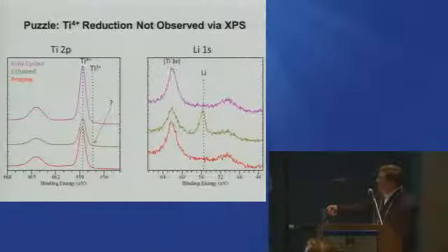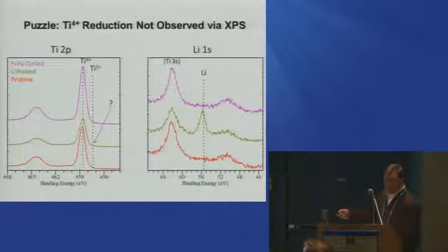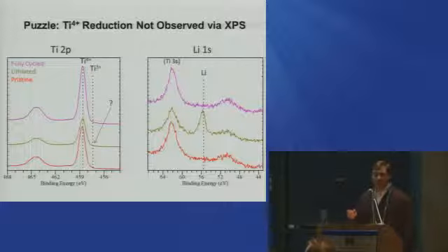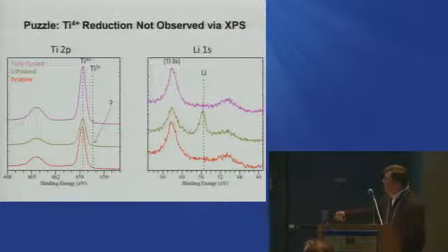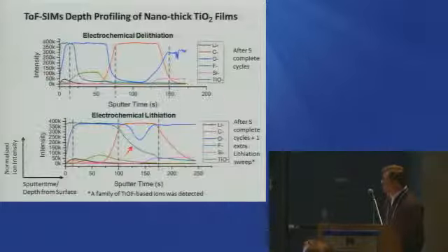But if you look at the actual XPS of lithiated anatase, these thin films, versus the delithiated ones, we actually see no change in the oxidation state of titanium. And so it's not just that we reduce titanium 4 to titanium 3 and it turns blue; there are other trapping mechanisms that don't report on the change in the oxidation state. And so in this particular case, XPS really isn't that sensitive to see if we actually have a small amount of titanium in there. But we do get lithium in these lithiated films, but no growing in of that titanium 3 signal.